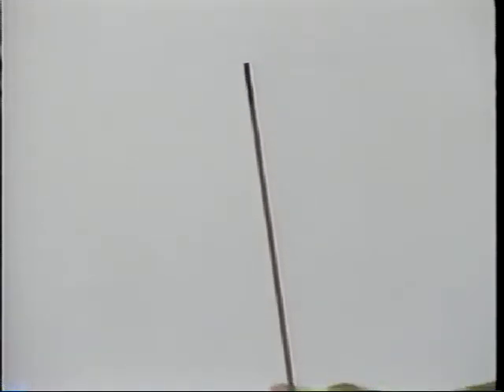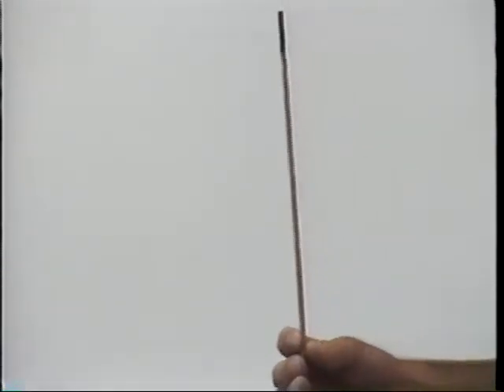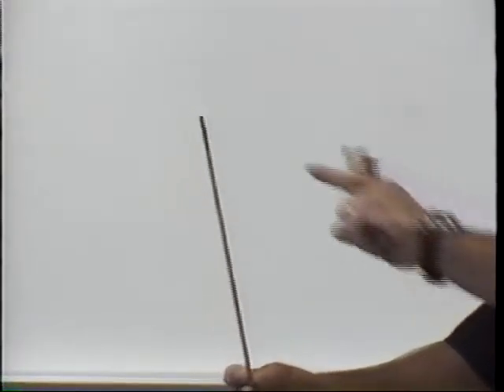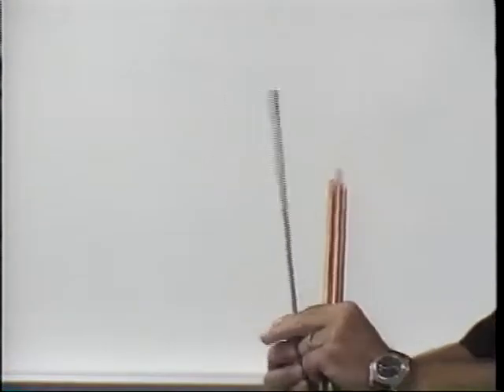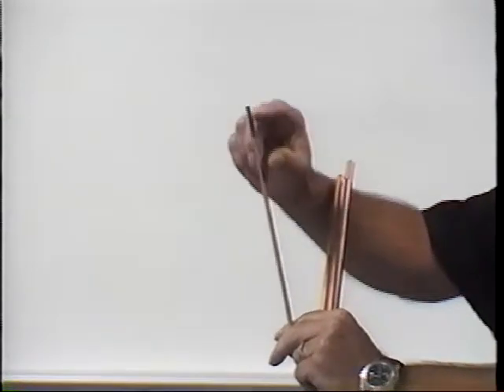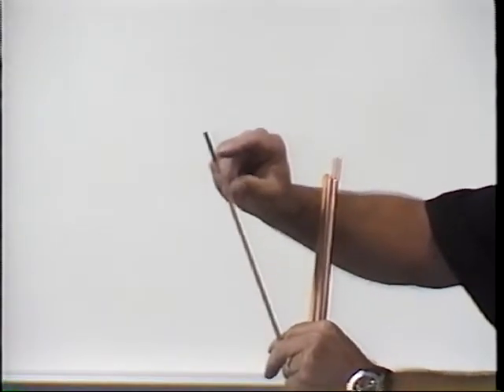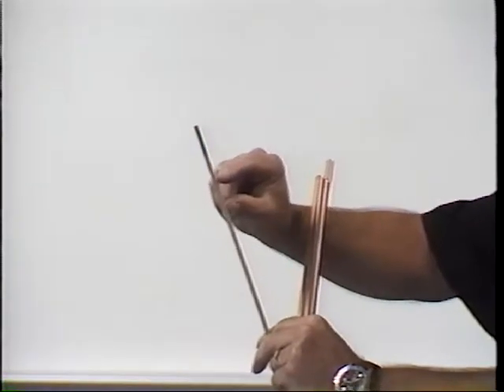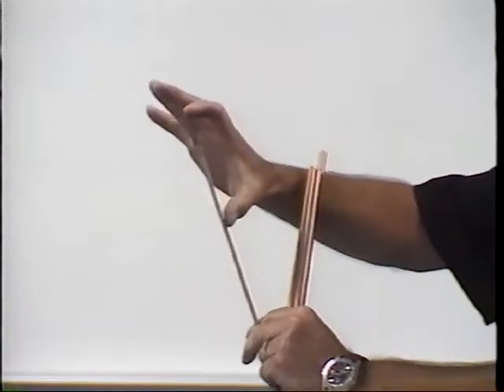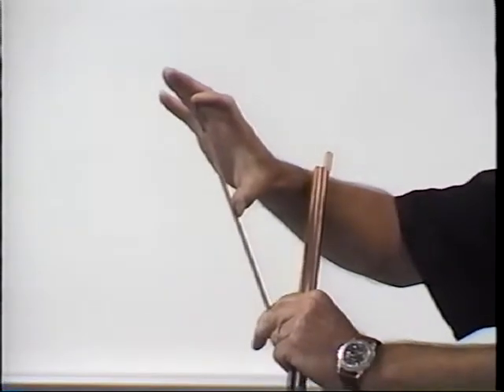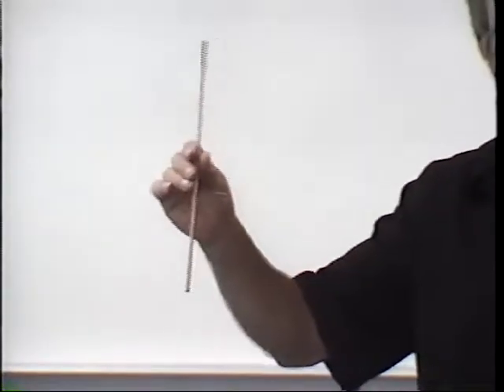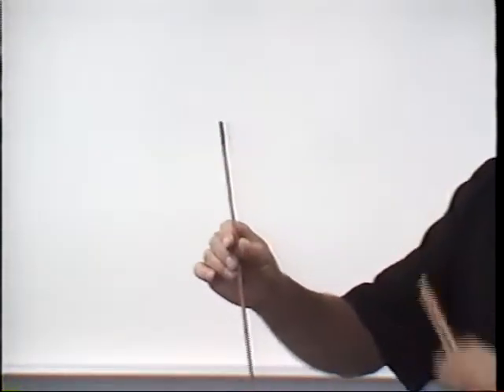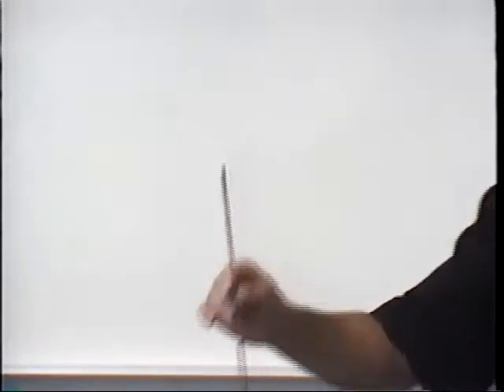And a good rule of thumb, if you're not sure if you're running the correct amperage, you see the tip here, this first part is graphite, and then the copper coating begins. If you want to know if you're running about the correct amperage, just watch as this burns away. And as this copper begins to burn away, of course this thing's going to be getting shorter, and you should always have about that much of the copper burnt away. If suddenly you've got this much graphite showing, you probably have too high an amperage for the size electrode that you're using. So let this be a guide to you to know whether or not you're using the correct amperage setting.